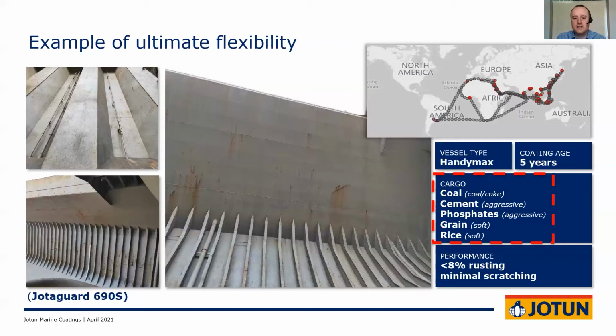And here we can see that there's no major issues being presented throughout the trade or the operations after 5 years in service. So here again, we would expect at this special survey docking to just do minor repairs of this coating again, and that coating we would expect to last at least another 5 years again. So an additional extension in terms of the interval between maintenance for these very specialized cargo hold coatings from 0 to 10 years, which is a good result and can significantly reduce the maintenance costs.